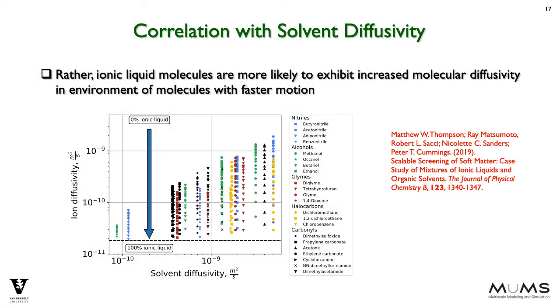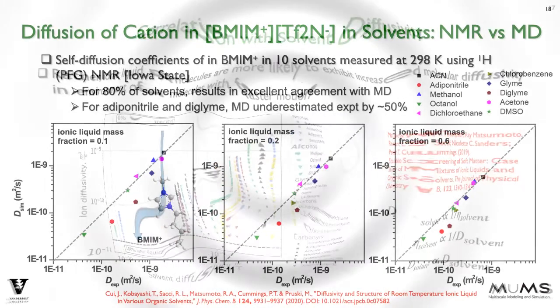However, if we plot the results versus solvent diffusivity, we see that there is good correlation. For dilute solutions, this is not entirely unexpected, since on the basis of Stokes-Einstein, we would expect for a dilute solution in a solvent that solute diffusivity would be inversely proportional to solvent viscosity. And then, since solvent viscosity is inversely related to diffusivity, this would suggest that solute diffusivity is proportional to solvent diffusivity in the dilute regime. The simulation data suggests that this is true well beyond the dilute regime.